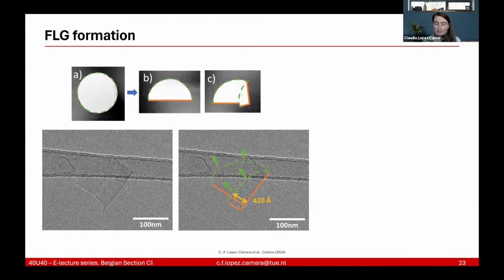Another good outcome of that picture was that we found this folding was 420 angstroms in length, and that was aligned with what we found in the literature, in numerical literature. It was not shown experimentally yet that it becomes unstable at some point. If you count from this folding of the sheet, you have 4 layers of graphene. That layer should be 420. That's when it gets unstable.